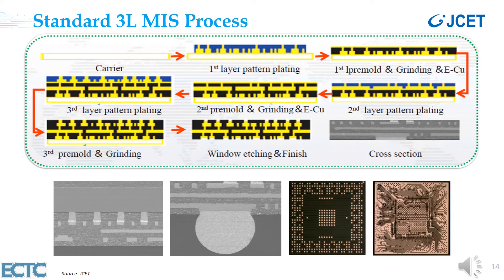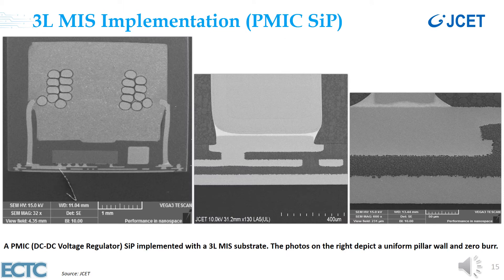This is the 3-layer MIS process flow, with the same stack-up practice as shown in the previous slides, and the same considerations about warpage and delamination. This is a DC-to-DC voltage regulator module implemented with a 3-layer MIS substrate. Notice the big passive component mounted over the IC die. The image resolution is enhanced from left to right at 1mm, 400 microns, and 50 microns respectively. As shown here, the copper pillar and resin around and between the layers are clean and have no burr.